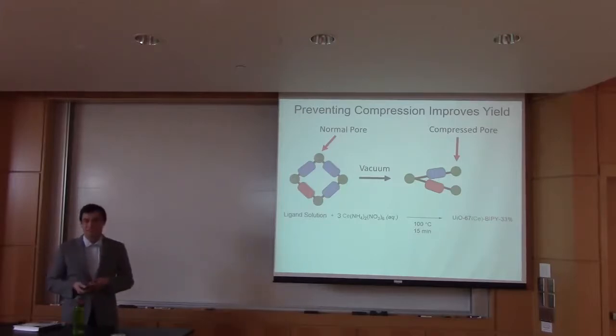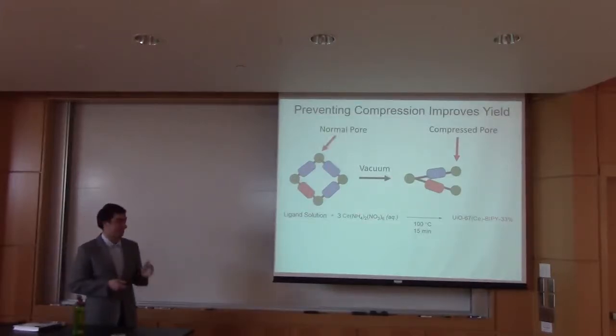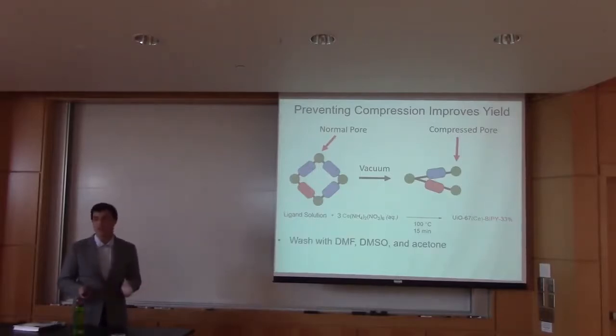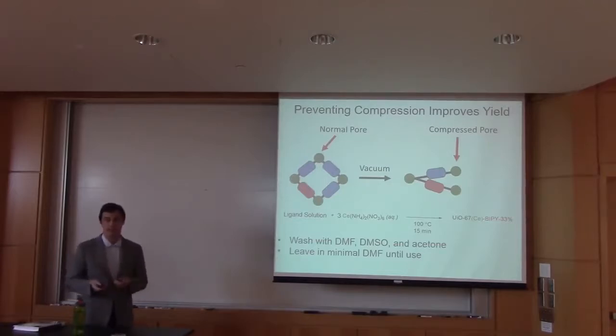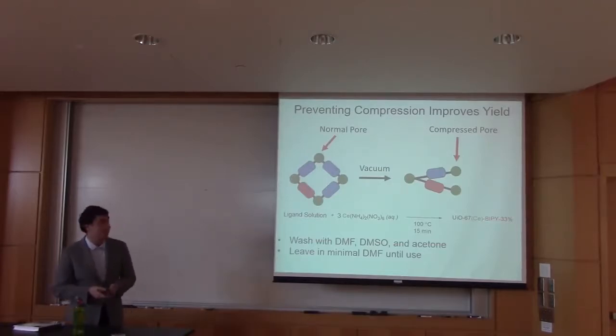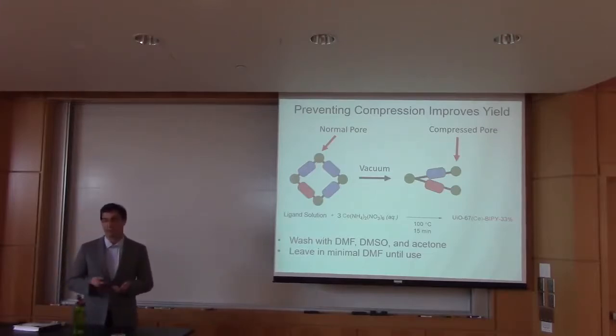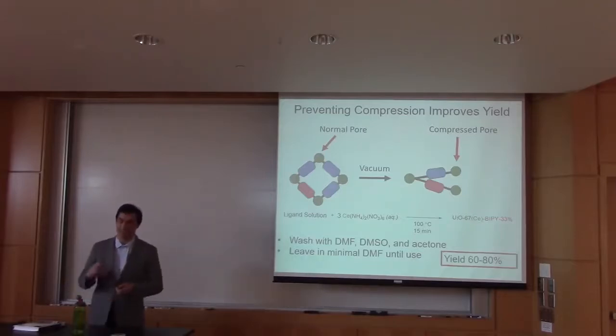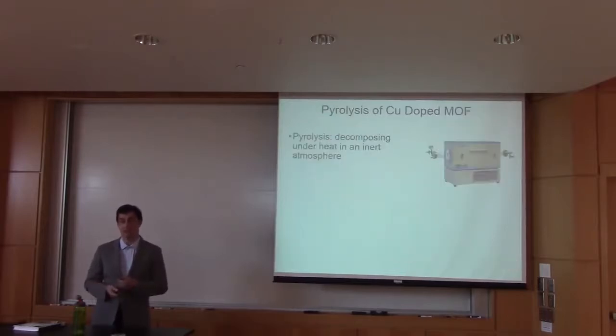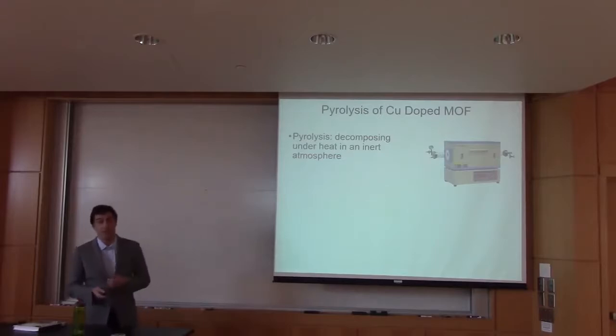To fix this, we did something rather simple, but it took a long time to get to. We made the MOF precursor, the pale yellow solid, just as we had before, and washed it the same way. Then, instead of pulling it under vacuum, which causes that eventual decomposition, we left it in DMF, then washed with acetone when we were going to use it and dried it for 2 hours as opposed to overnight. That gave us a great increase in yield, which was fantastic, and allowed us to continue forward making this catalyst at a larger scale and move to the next step, which is pyrolysis, as we go to make this active catalyst.